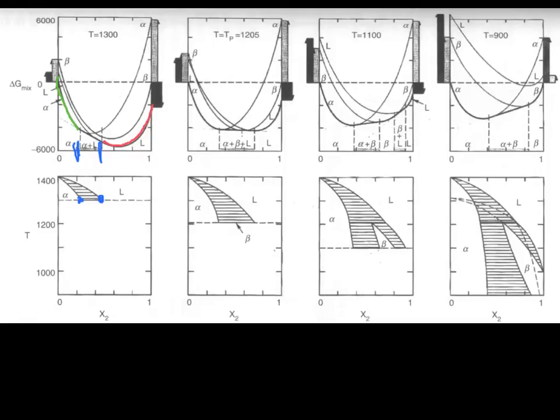Now, what happens here is that the beta curve is also starting to come down, but, unlike what happened in the eutectic case, where we had alpha on one side, liquid in the middle, and beta on the other side, we now have the liquid curve coming down on the side, instead of coming down in the middle. And, apparently, peritectic somehow means, from Greek, that this is melting on the side, and that's just showing that the liquid curve is on the side and not in the middle, whereas eutectic means melting in the middle. So, this has the liquid over on the side.